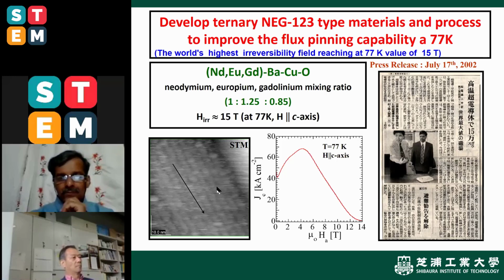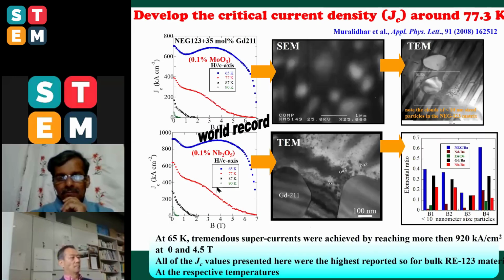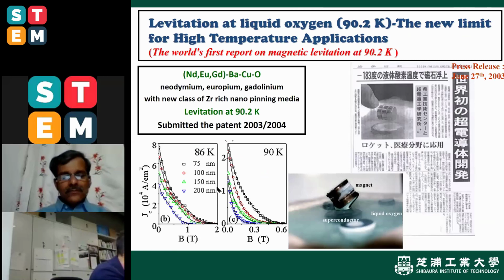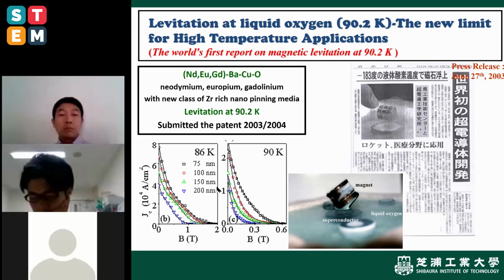Further, our main aim is to improve the critical current density. We again concentrated on many things like niobium nanoparticles and molybdenum nanoparticles. As a result, we found a new type of 211 particles, and the critical current density was improved at 90 Kelvin. That is the liquid oxygen temperature. As a result, one can levitate the material at liquid oxygen temperature, not liquid nitrogen. You can see the figure, the blue color is liquid oxygen.